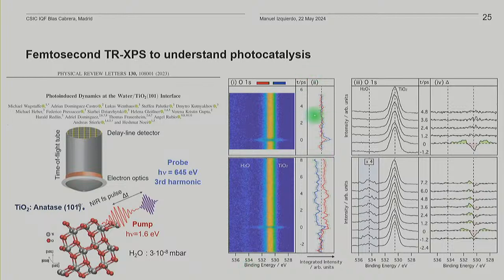However, you can see that there is no change in the position of the peak. So basically, there is no surface photovoltage effect, and this is proof that your surface is as stoichiometric as it could be. On the contrary, if you now adsorb water, basically less than one monolayer, around 80% of the surface was covered, you see here a faint line showing up that is related to chemisorbed and physisorbed water.